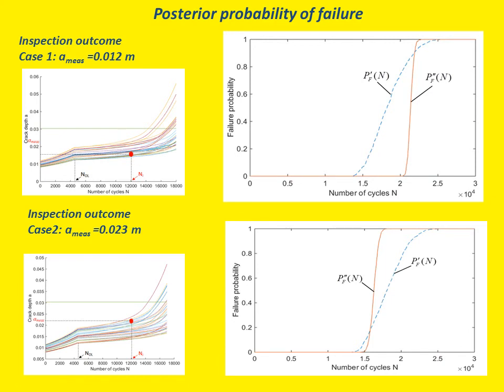Here are the dependencies of the posterior probability of fatigue failure for two cases of inspection results related to the numerical example considered earlier. Case 1. The size of the measured crack is rather small. Case 2. The size of the crack is closer to the critical value. It should be noted that due to the reduction in uncertainties, the posterior curves are more abrupt than prior curves. For the larger crack length measurements, the posterior curve moves to the left, for smaller crack to the right.